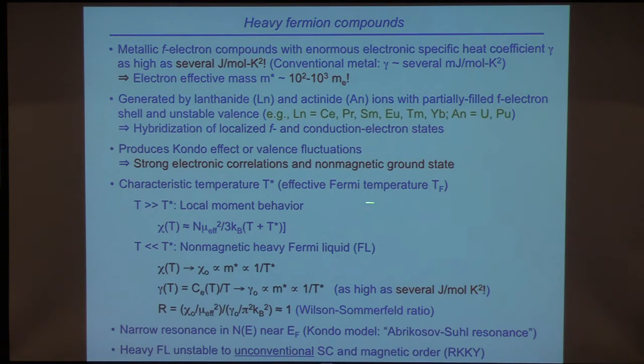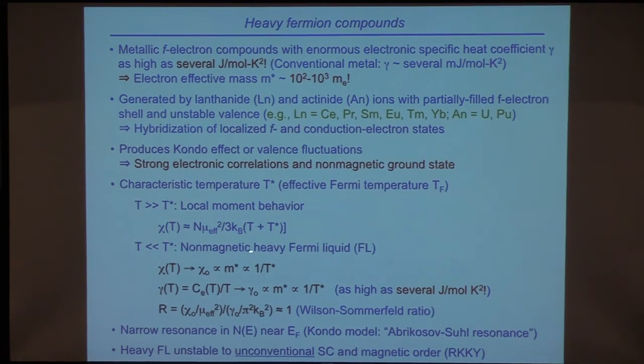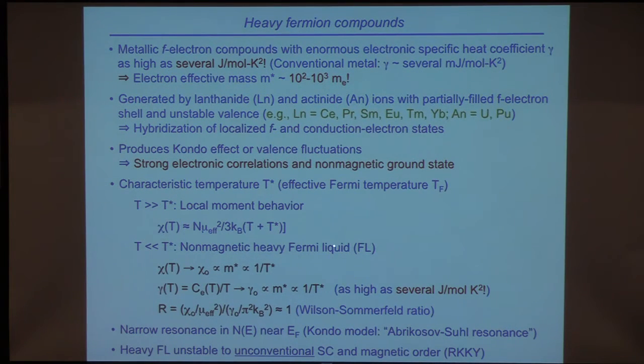And so what you find is that there's a characteristic temperature, we'll just call it T star. It could be a Kondo temperature, it could be a valence fluctuation temperature, but it acts more or less like an effective Fermi temperature. And so at temperatures much larger than this, you find local moment behavior. The magnetic susceptibility behaves like a Curie-Weiss law with a moment close to the free ion value. And then the Curie-Weiss temperature, T star, is not a measure of where magnetic order occurs. It's a measure of the interactions that produce this highly correlated ground state. And then at low temperatures, as I said, you get a non-magnetic ground state. It's a heavy Fermi liquid.